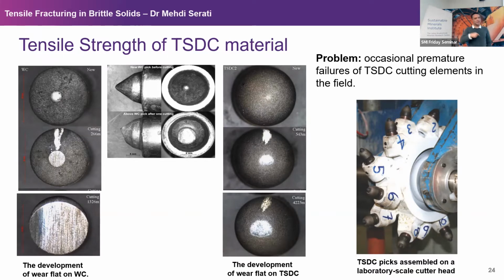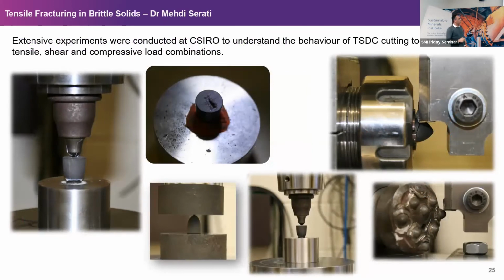The problem, though, and that's when I got involved in this project, is that you test the rock cutting with this new technology, beautiful, everything is a tick. But then when you go to the field, those TSDC cutting picks suffer from premature tensile failure. Why? That's when I got involved. I proposed that one potential reason is that we are measuring the tensile strength incorrectly, because we are using the Brazilian test, and there has been a debate. So I proposed that the value of the tensile strength that we get is potentially incorrect. We need to find an alternative method to get it right, and then redesign based on the new tensile strength.